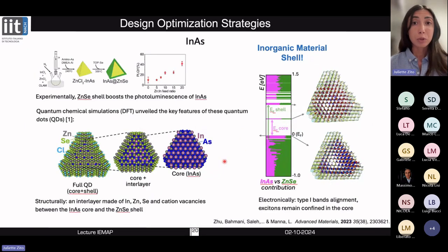And again, in the context of the IEMAP platform, another material that was studied, as Luca also described extensively before, involves growing an inorganic shell around III-V semiconductors, in particular indium arsenide. We saw before that these types of materials are very sensitive to the formation of trap states upon detachment of Z-type ligands. So a good strategy to avoid this detachment is to grow an external shell of inorganic material around this indium arsenide core. Experimentally, doing so was found to boost the photoluminescence of the indium arsenide from 10 to above 40%.